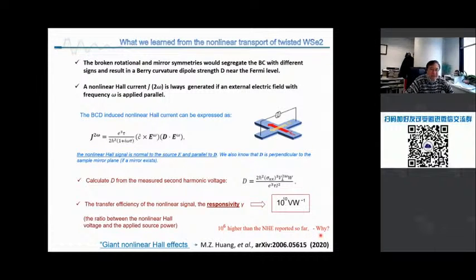The problem is how to explain this? We need theoretical groups to work together on this. So far, we do not have a conclusion, but we know it is related to this very interesting moiré pattern formed by twisted TMDCs. Yeah, you may ask, has anyone observed such a nonlinear Hall effect in graphene? Not yet. If you have interest, do it. You should see it once you can introduce strain. But the key point is that if you want to introduce maximum strain, you need a small twist angle.